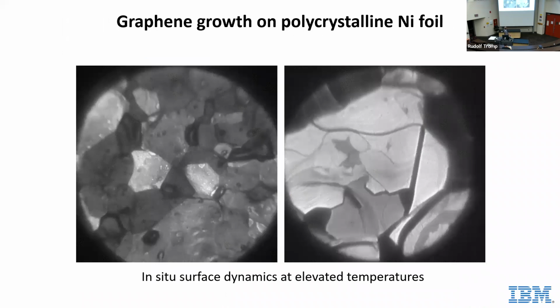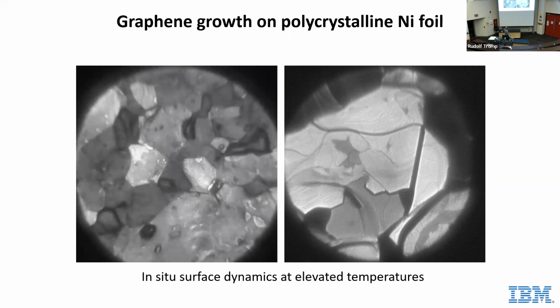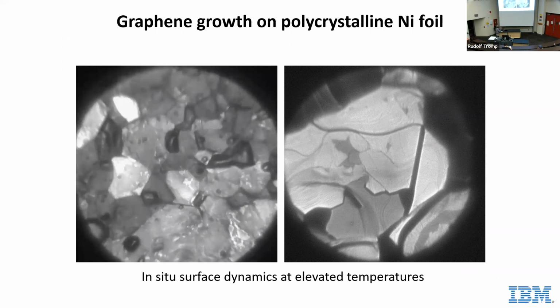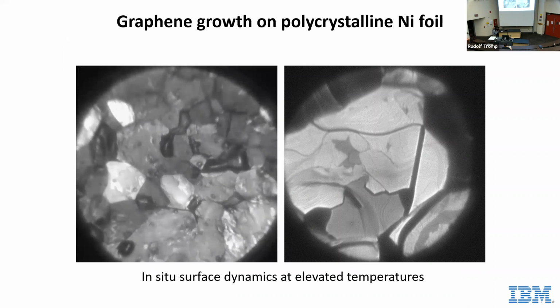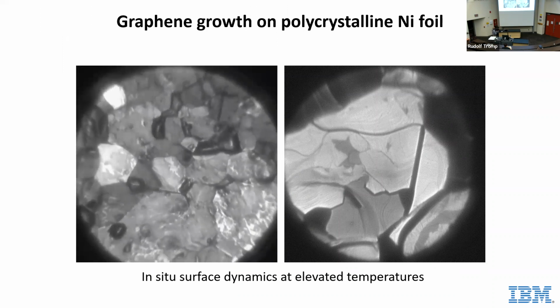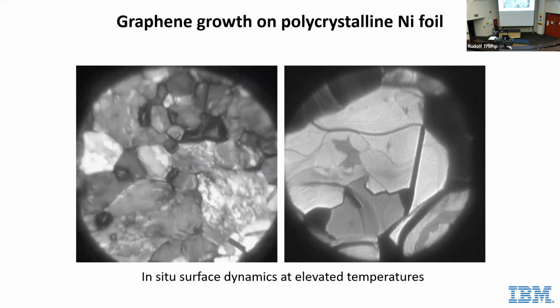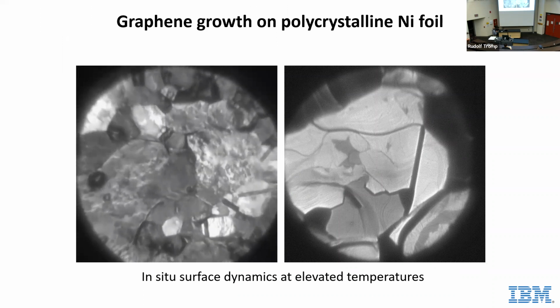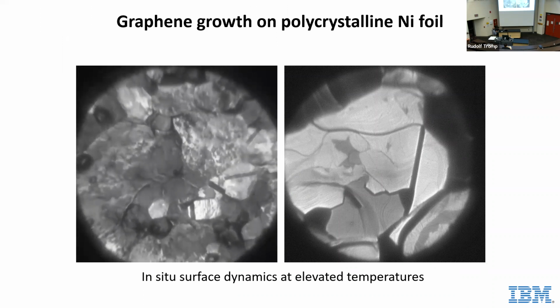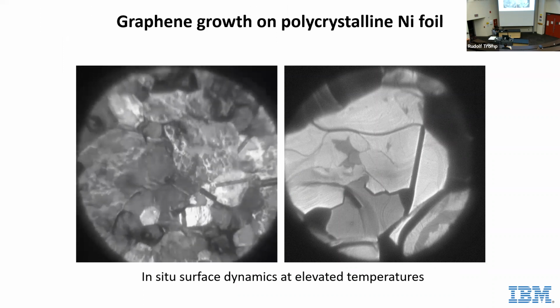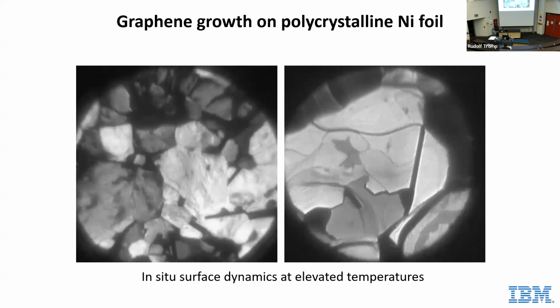One of the beautiful things about LEEM, of course, is that you can do live microscopy with it, which is why I got interested in the first place. On the left here is a movie of a polycrystalline piece of nickel. So just a nickel foil that I pulled out of a drawer, and you see the grains, and I'm slowly heating up the sample now. If you look here, you see some of those grains get punched out of the film. I think it's this grain here, but she'll start shrinking. There's all kinds of changes on the surface.